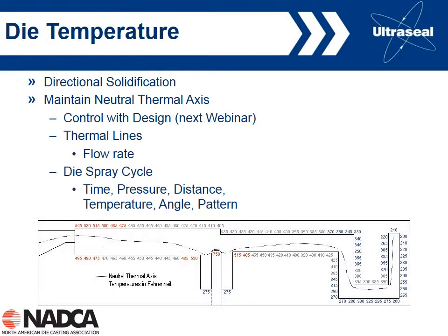So let's talk a little bit about die temperature. This is really the last category that can have a big impact upon reducing porosity. The goal here is to get directional solidification, as we talked about. If we can get directional solidification from the extremity of the casting back towards the gate, that helps us feed the shrinkage, because the additional metal we're feeding with is coming through the gate. And so avoiding isolated heavy sections in the casting is a good thing. Over the next few slides, we're going to talk about thermal control in the die, the effect of thermal control from internal cooling, and effective thermal control from spray, in terms of how those can actually affect our porosity and how much control we really have over each of these two processes.